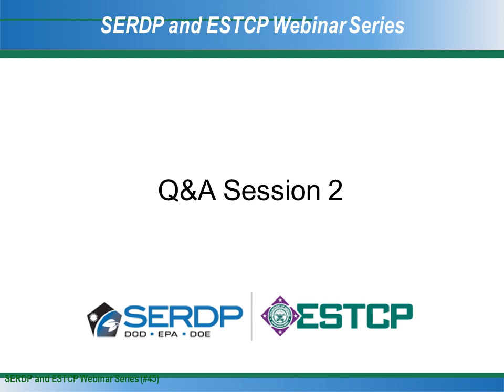This is Mark. So I think that the challenge, we've always been able to produce low gloss powder coatings, but the chemical agent resistant coatings add even lower gloss than is typically used in commercial applications. So getting stable low gloss with a smooth appearance that doesn't look like sandpaper, a huge amount of texture as has been used in low gloss coatings. So getting a low gloss with an acceptable appearance, and then you combine that with the chemical agent resistance, because as you flatten it, then you make it more porous. So combining low gloss with chemical agent resistance, and then ultimately the exterior durability. So all those combinations. But a lot of it comes back down to low gloss and chemical resistance.